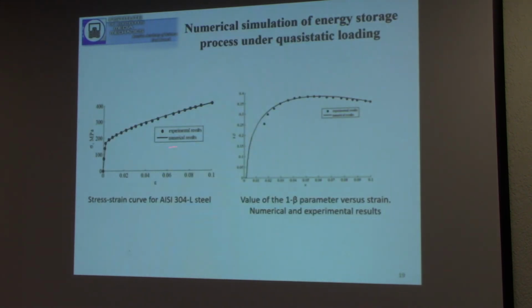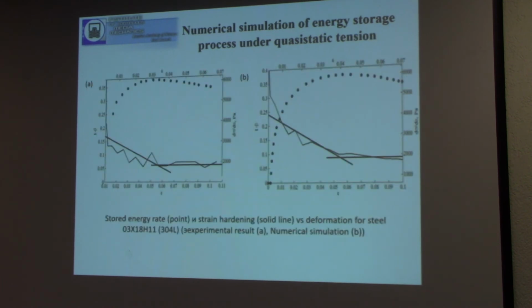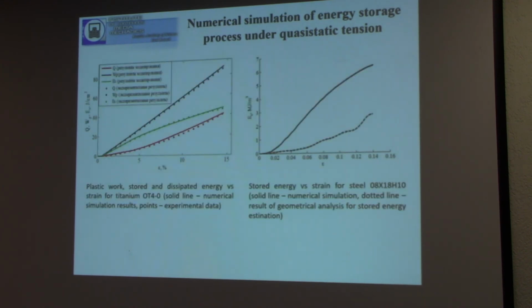And here you can see the results. For example, it's the mechanical parts, the dissipative part, the stored energy rate for steel. It's very interesting. We can find some very fine parameter. For example, here are the experiments, here is our simulation. Here you can see the stored energy rate. Here you can see the hardening coefficient. And there is a key point on the hardening coefficient which corresponds to the maximum of stored energy rate in experiments. And the same we can obtain in numerical simulation. There is a key point in the hardening coefficient, and it's the maximum of stored energy rate. And in the next slide, I will speak just about this.